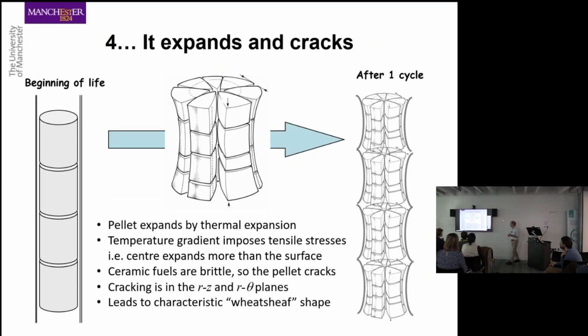The fuel expands and it cracks. We don't really have time to go into why it expands like this, but it actually does. And this is not really a nuclear effect. It's an effect that you will observe in any brittle material that is exposed to a parabolic temperature gradient. In other words, higher temperatures in the middle, smaller temperatures on the outside. So it's nothing to do with the fact that it's in a reactor. This is the fact that this brittle material is trying to expand significantly in the middle and trying not to expand very much on the outside.